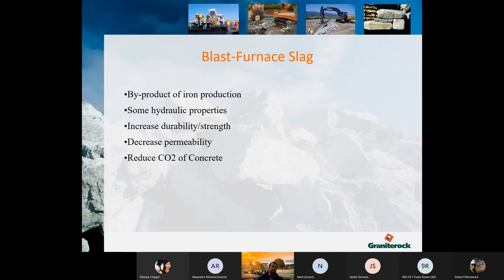So blast furnace slag, like other SCMs, work by combining with the byproducts from the hydraulic reaction of the Portland cement. Basically, it uses leftover alkalis to create more crystals due to the chemical makeup of this. And when it does that, you are basically gaining more strength with the same amount of cementitious material. And because of that, it's filling the voids in concrete that wouldn't have been there. So that decreases the permeability. We'll talk about the CO2 effects of concrete later, but this does help to decrease that.